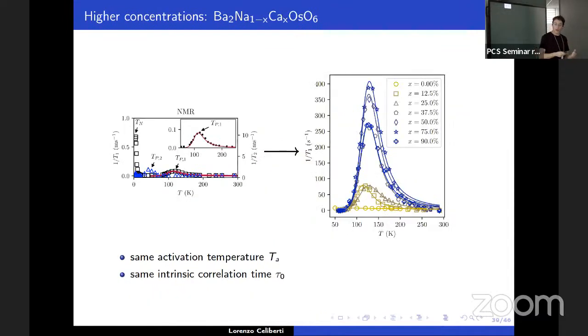So then we observe this peak also at higher concentrations of calcium. And this is basically how the peak changes. What we observe is that the position of the peak, the activation temperature, and the intrinsic correlation time tau 0 are basically the same at every concentration measured. The only thing that is changing is the height of this peak.